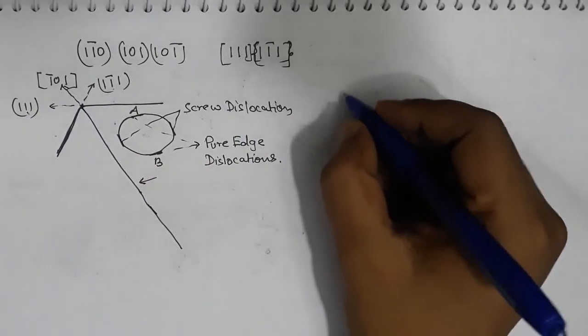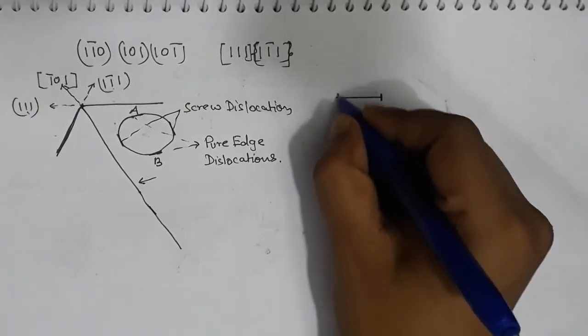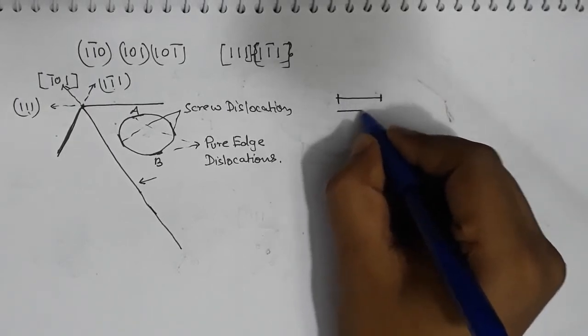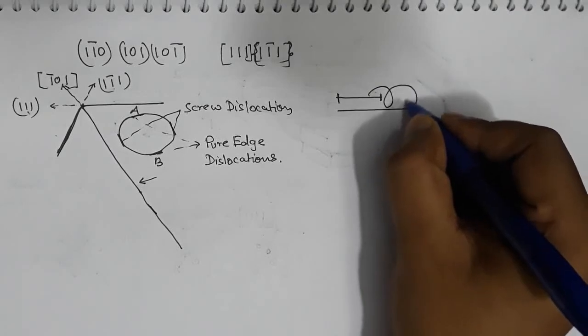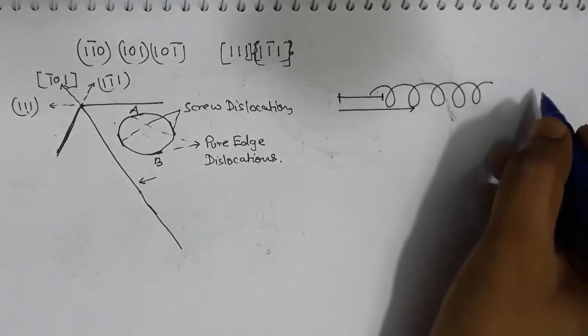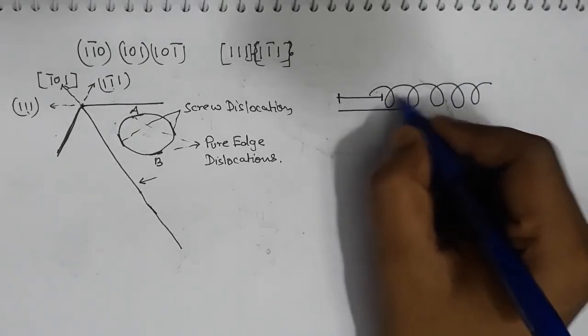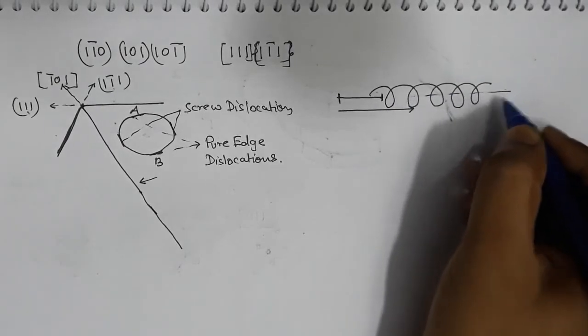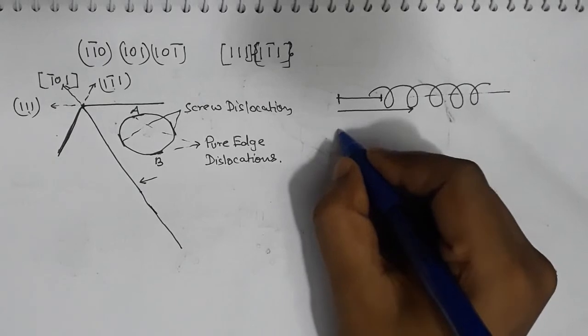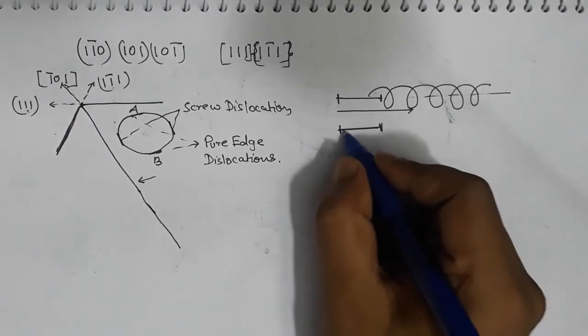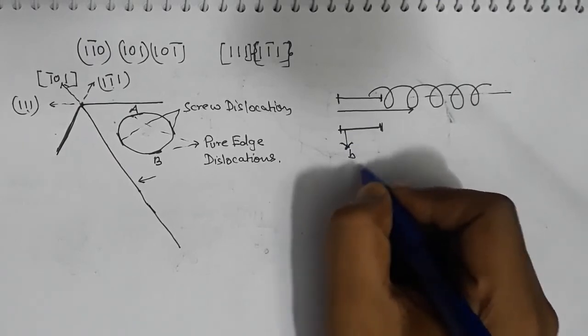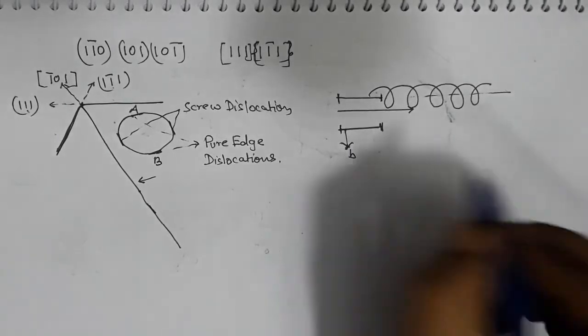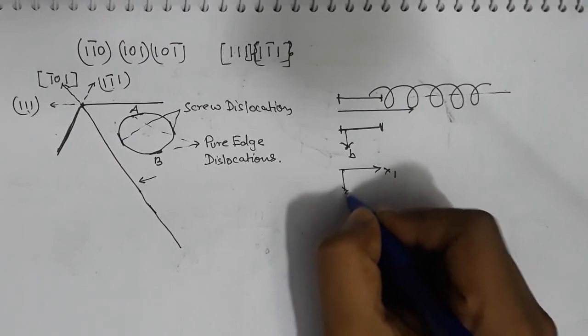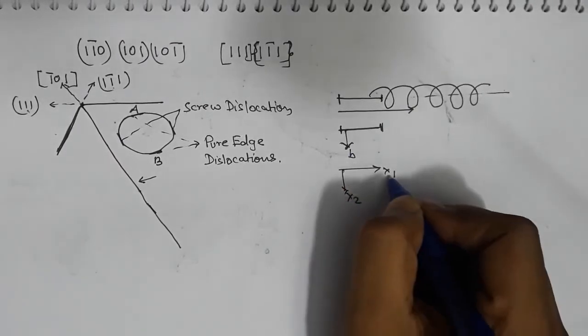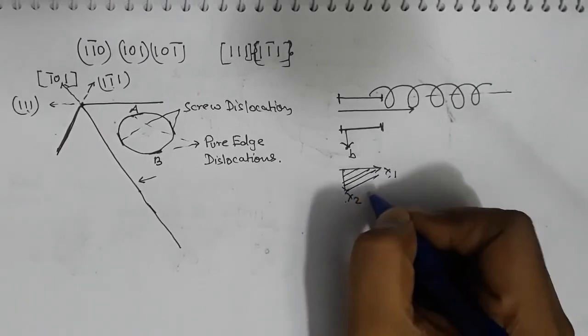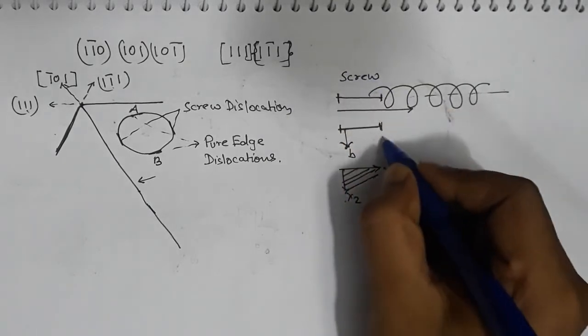You will have to understand this part. Let's say this is my screw dislocation, and this is the line of screw dislocation, and it is moving in this direction like a helix. So it doesn't require a plane to move. It is a line which is moving along the line, so it doesn't need a plane. But for an edge dislocation, if this is the line, then the Burgers vector has to be perpendicular to this, and therefore an edge dislocation needs a plane to move. If this is the x1 and this is the x2 direction, then this edge dislocation can only move on the x1 x2 plane. So it requires a plane to move. Screw does not require a plane to move. Edge requires a plane to move.